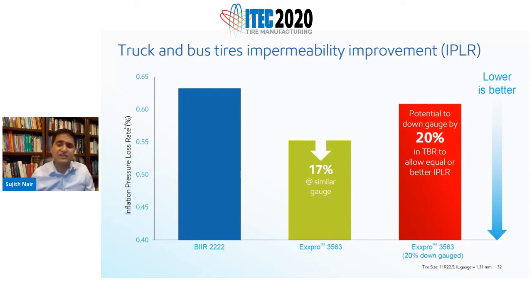Now, what we did was we actually reduced the thickness by 20%, and you can get almost a similar or better performance compared to the BIIR 2222. So you can see that with X-Pro 3563, there is a potential to down gauge, and this becomes more important in larger tires such as TBR. This is an 11R 22.5 trial that we did, where the inner liner thickness was around 1.5 millimeters.